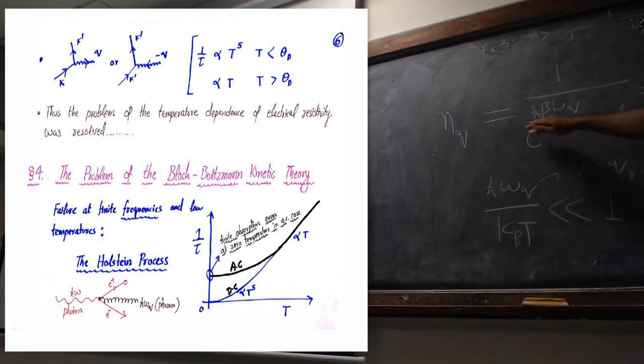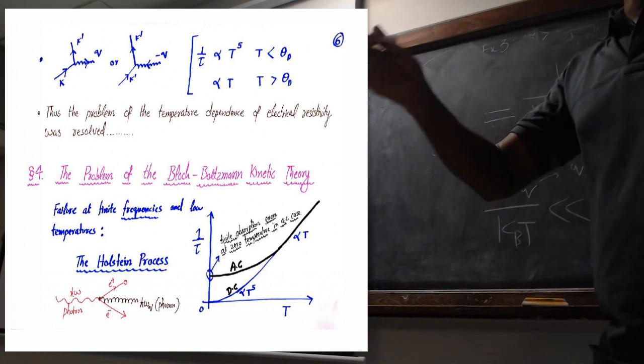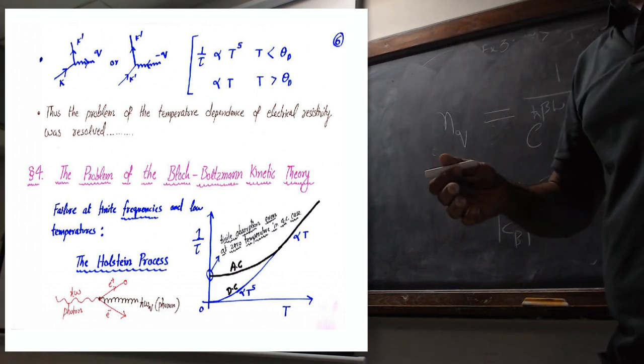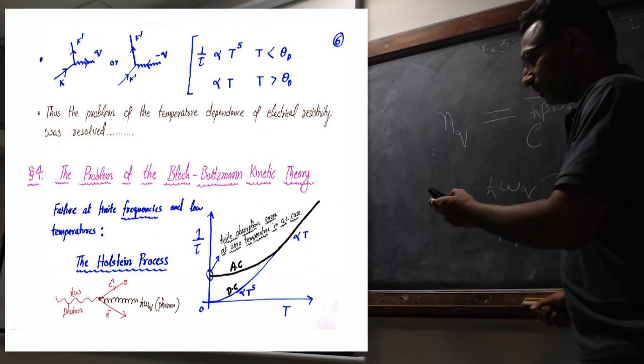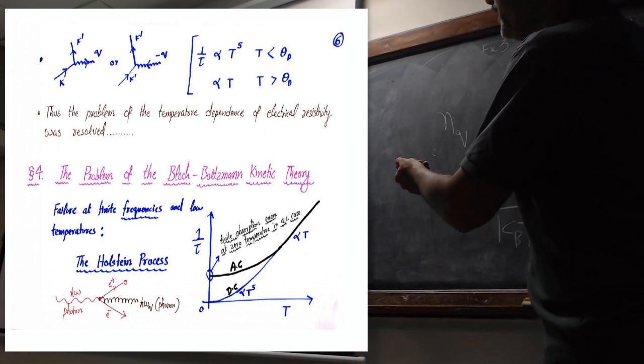I mean, you Taylor expand it. It will be k_B T upon that energy scale, ħω_q. It's proportional to temperature. So I will Taylor expand it: 1 plus ħβω_q plus all of the higher terms, minus 1. So I am neglecting the higher terms, and I have ħω_q divided by k_B T. k_B T goes upstairs, so k_B T upon ħω_q. So this means that at high temperature, the number of phonons is proportional to temperature. So the number of scatterers is larger as the temperature is larger. That's why you get T-linear behavior at high temperature.